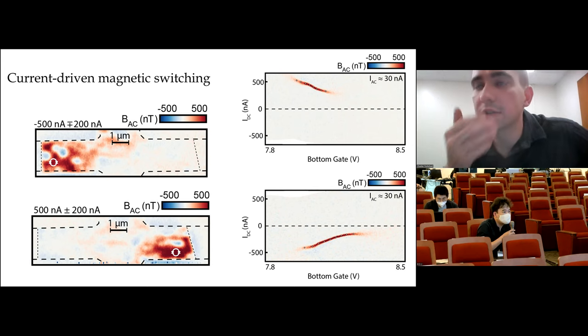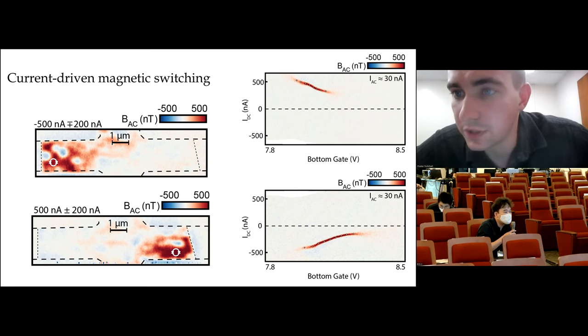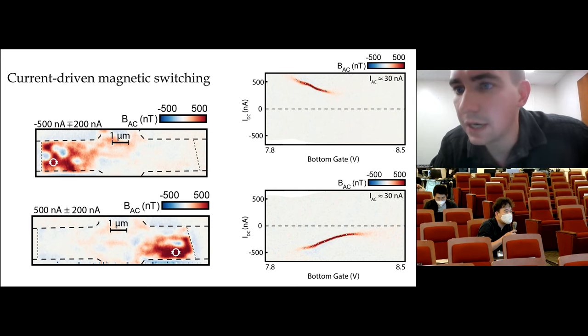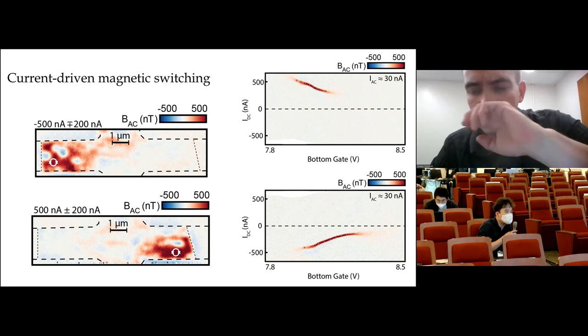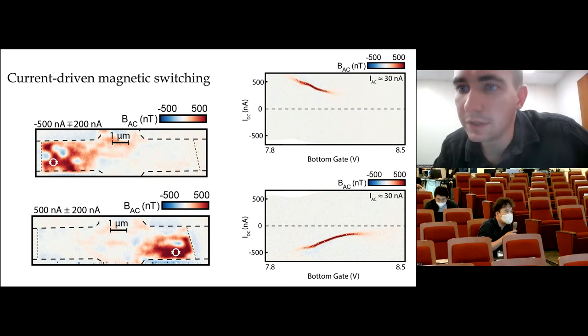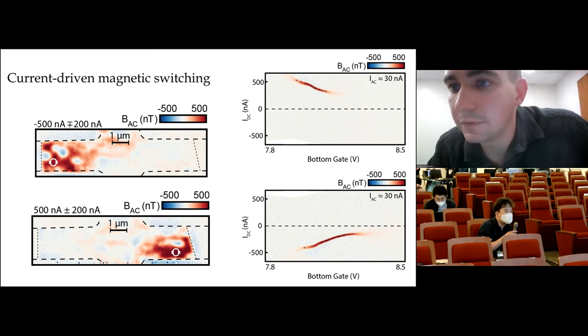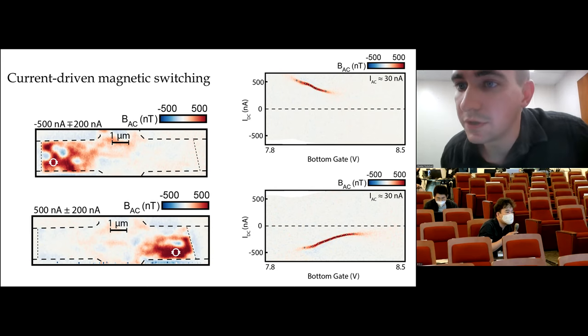First of all, one way that you could do what you're saying is just to go to high temperature, and then have charge carriers in the other Chern band just thermally. That's an experiment we didn't do in this system for basically technical reasons. The SQUID we were using had too small a critical temperature to image in that regime. But it might be what's going on in twisted bilayer graphene, which also shows this current switching phenomenon. It might be that because we were measuring at 6 Kelvin, which is probably a high enough temperature to get some electrons into the bulk, we were exerting a torque with those bulk electrons.